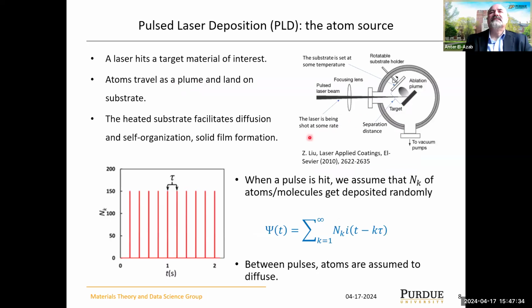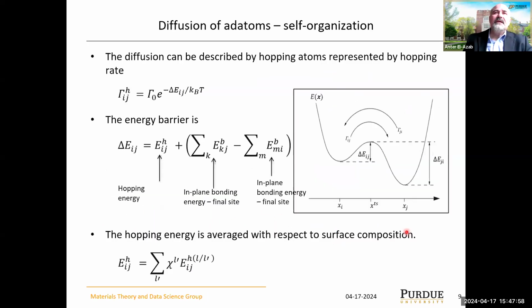So in this KMC framework, material comes in patches. Again, we simulate this deposition as pulses with a given magnitude coming in time. This is called a Dirac comb function or something like that. It's a superposition of impulses coming in. This is your material deposition rate. And when the material comes to the surface, it bonds to the surface and hops from one surface site to the next. So we look at the energetics of this process in terms of two energies that both contribute to the final hopping rate.